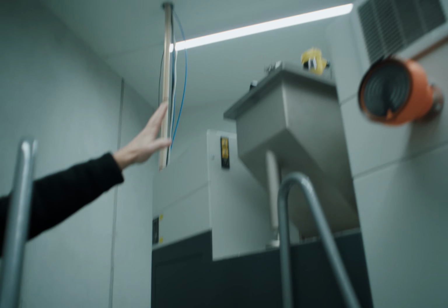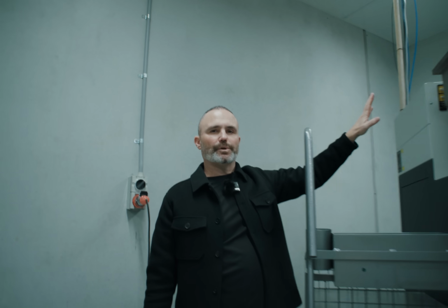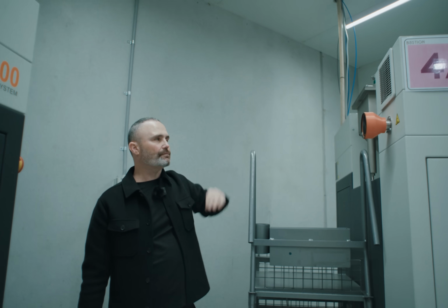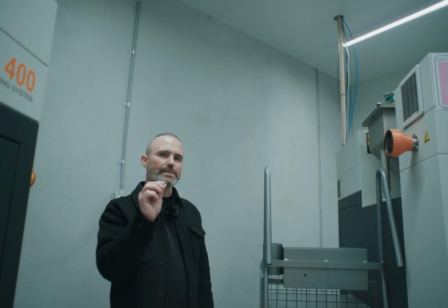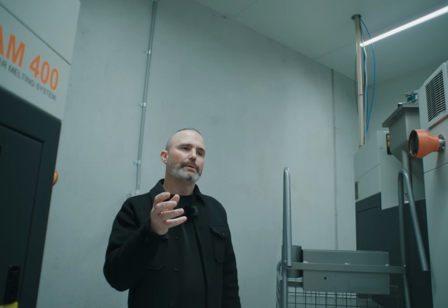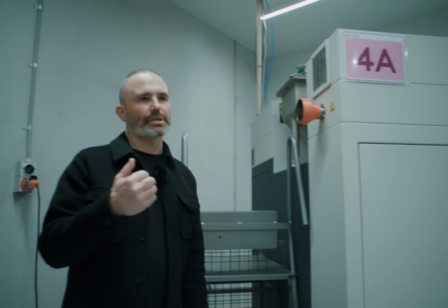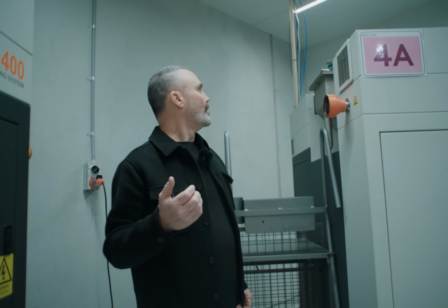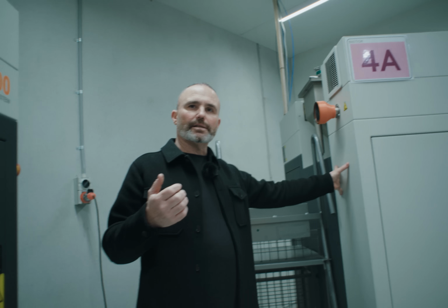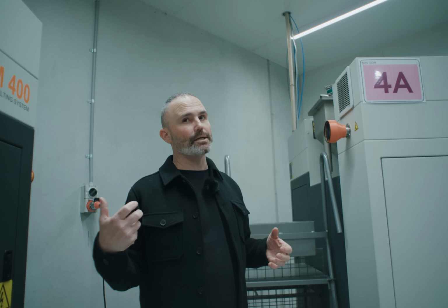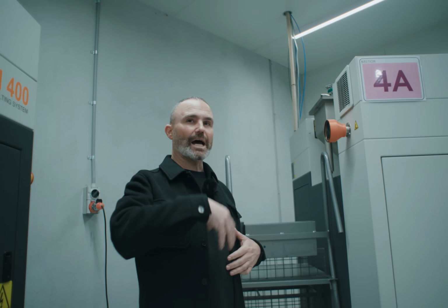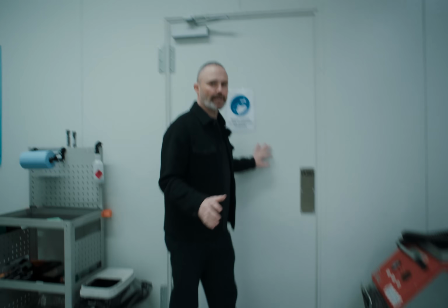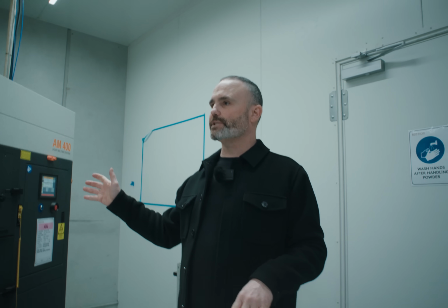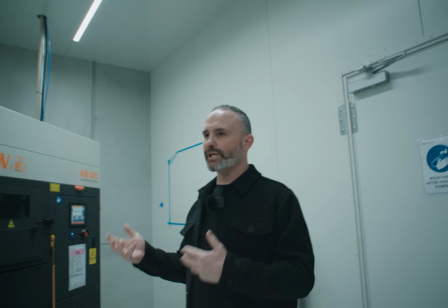So the powder itself is quite explosive when exposed to oxygen. It's very reactive. It's in such a fine particle system that it can easily explode, but also when it comes into contact with oxygen, it can get degraded. So everything that's happening in the machine is under an inert environment, so there's argon in there. The machine's sucked down with a vacuum, they pull all the air out of the machine, and then they refill it with argon. So after the printing process is finished, we do what we call a flip and we change it over.